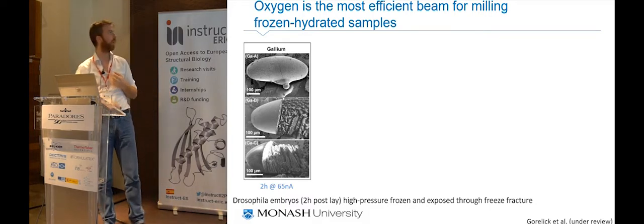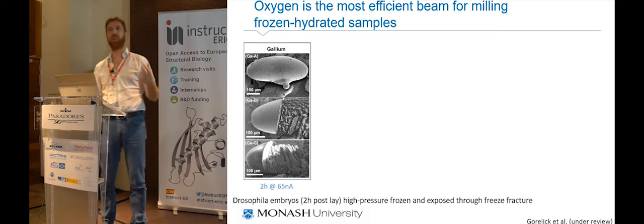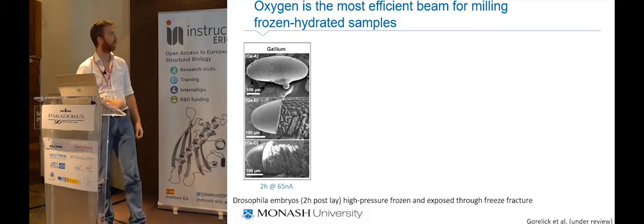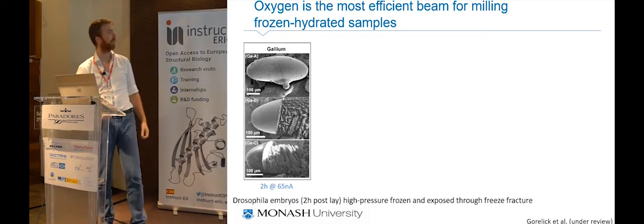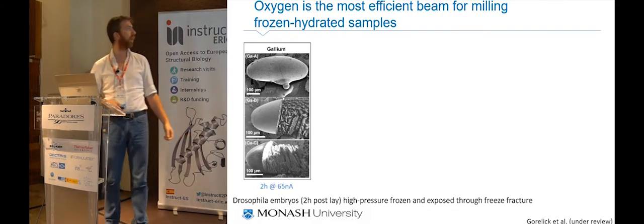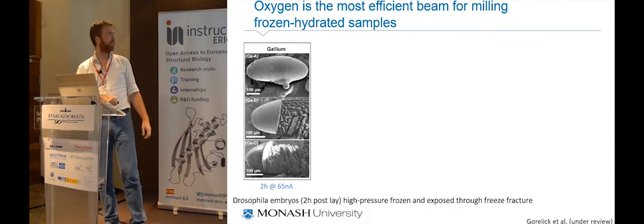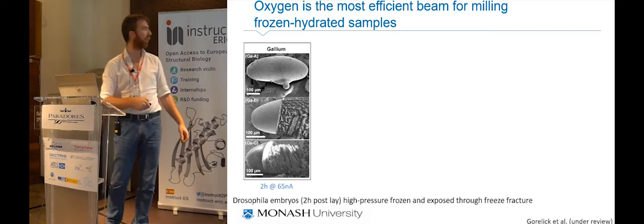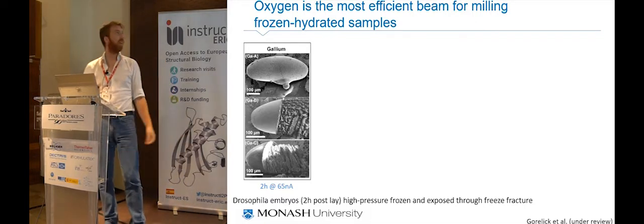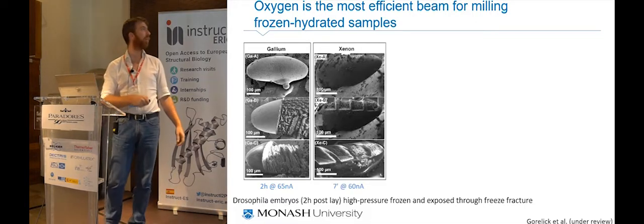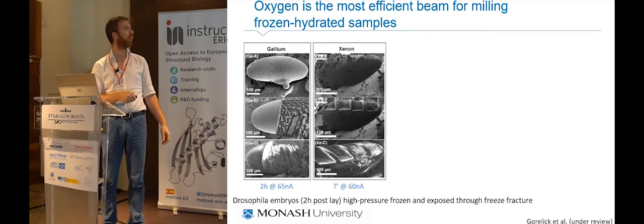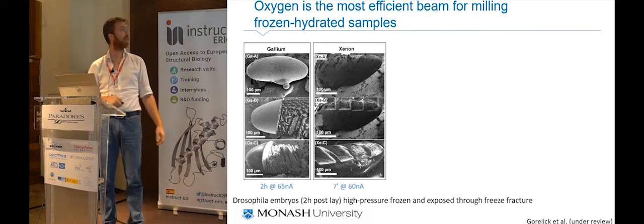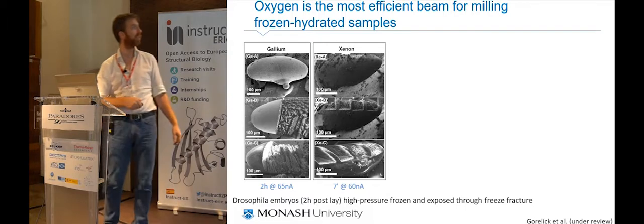So we used gallium, and you see, after 2 hours, at 65 nanoamps, which is the maximum current I can extract from a gallium FIB, this is what you get: all these pillars, and it just doesn't go away. This actually happens after pretty much 20 minutes, and then nothing changes. Then we use xenon. Xenon is a bit better. In 7 minutes we can cut this little thing, at 60 nanoamps, but that's about it. And the surface is really rough.